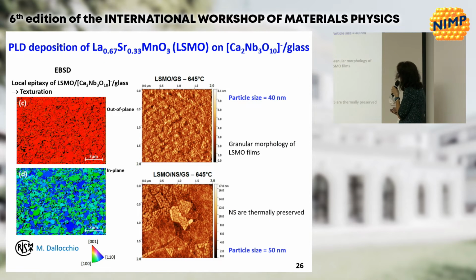This result was confirmed by electron backscattering diffraction, and you can see here the strong texturation with this out-of-plane map, while in plane we don't have any ordering actually. By AFM, we can see that the films present a granular morphology when they are directly deposited on glass. And here we can also see below the form of the nanosheets, which is preserved.